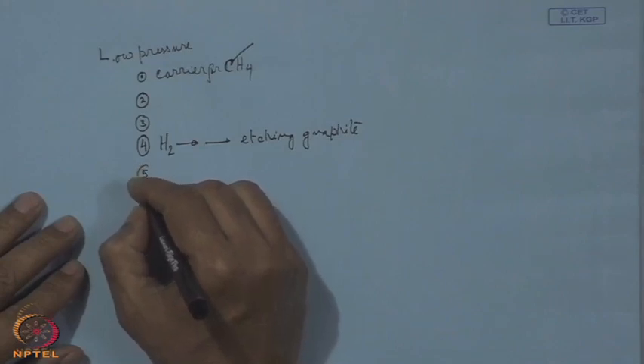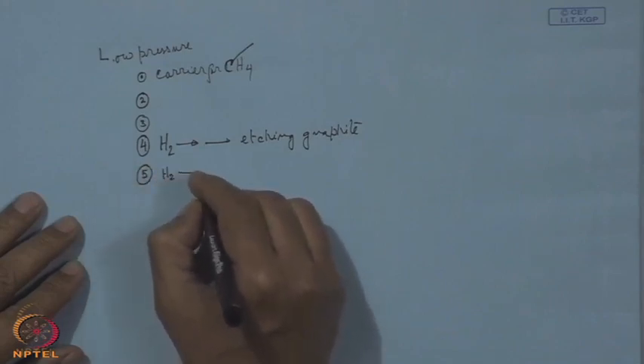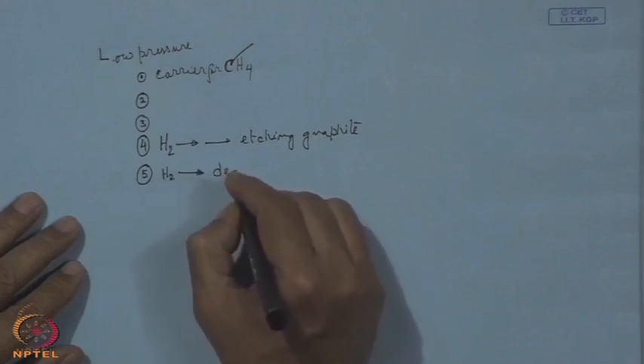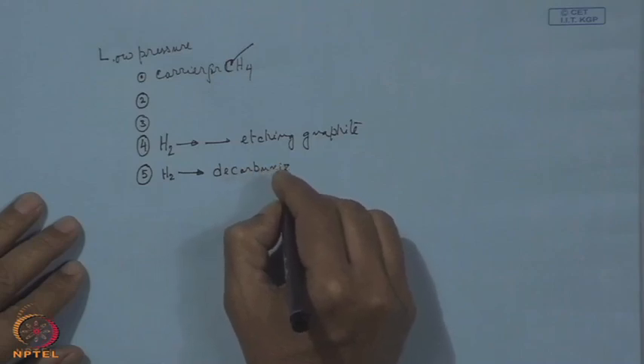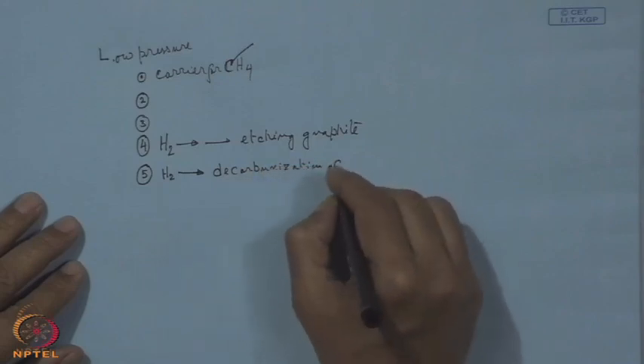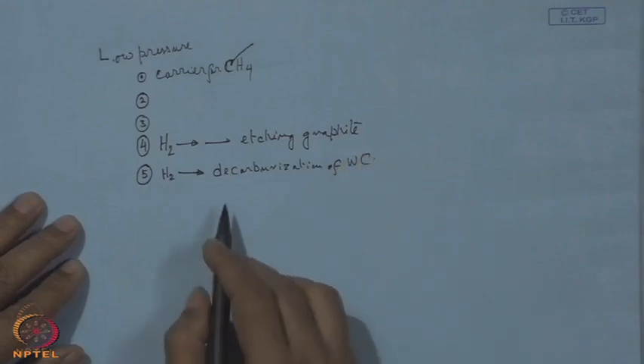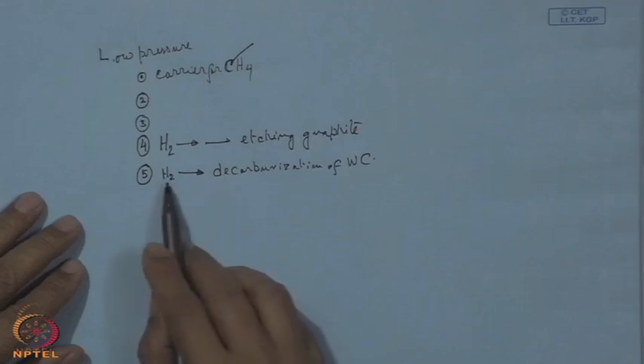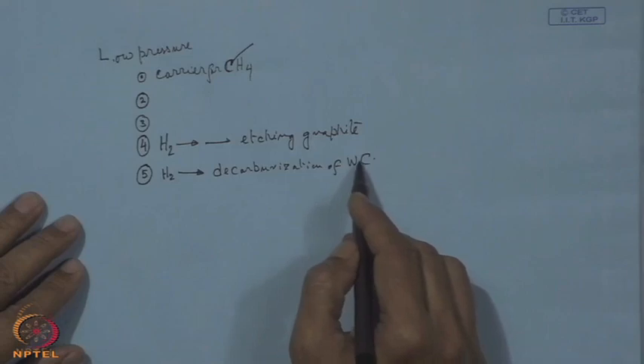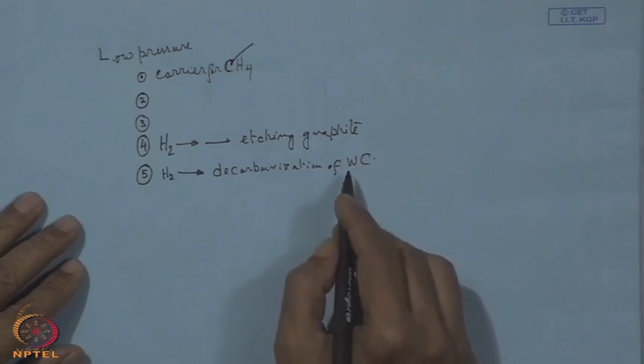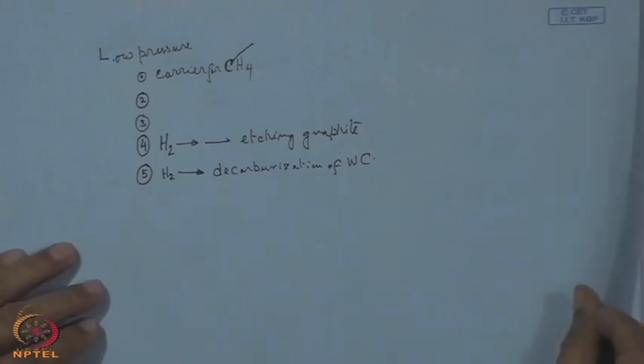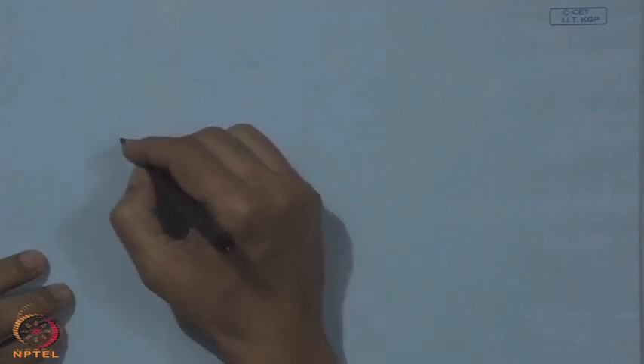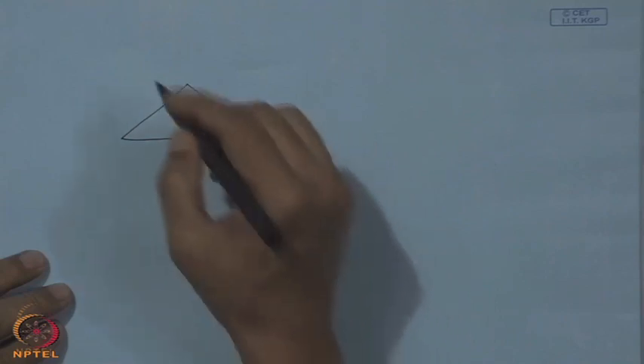There is another role of hydrogen, called decarburization of tungsten carbide. This is also one important role of hydrogen, to decarburize and reduce it to metallic tungsten. Now, here what we find is that if we look into this lattice of diamond, then one can find that it is actually a tetrahedral structure.